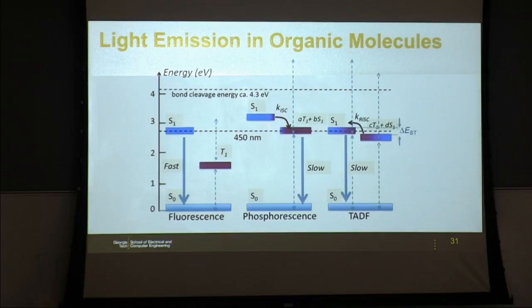And the new one is so-called thermally activated delayed fluorescence. The concept is that by playing with the molecular structure, you can control the energy difference between the singlet and the triplet. If you make that energy difference sufficiently small, and remember you're at room temperature, so you have that extra kT thermal energy, you can have what's called reverse intersystem crossing, where these triplet states re-excite the singlet states from where you can have light emission. So in that process, you can also have 100% efficiency.